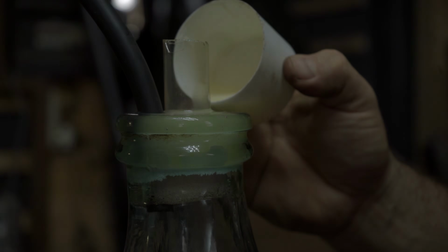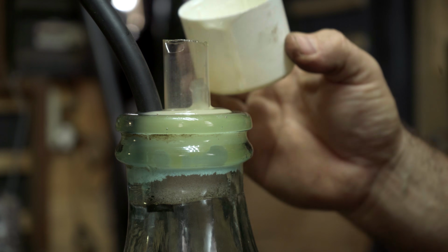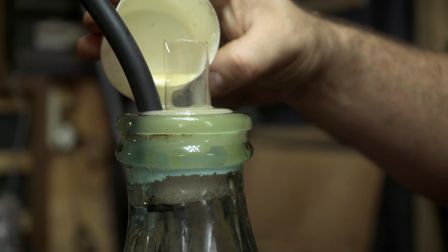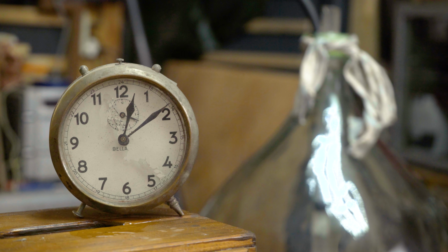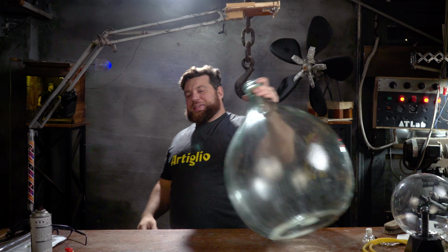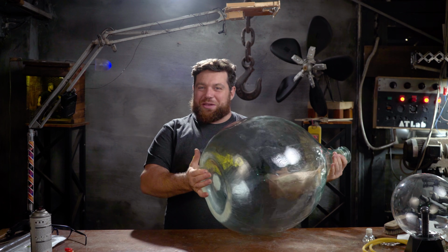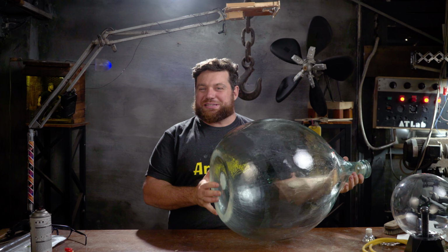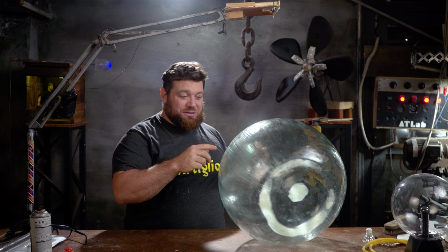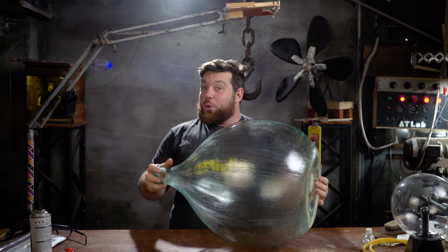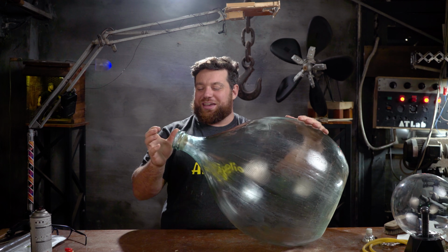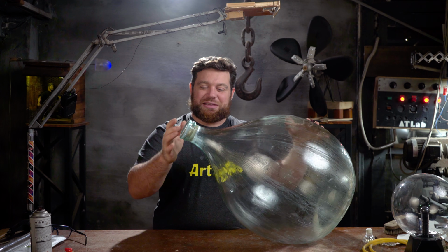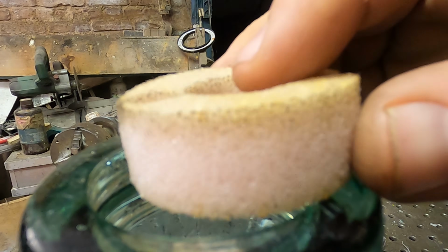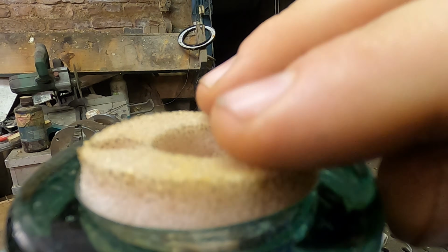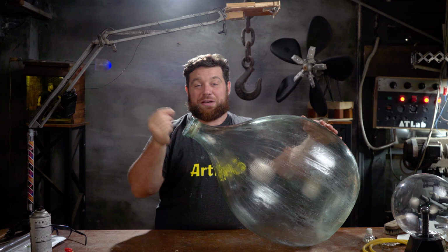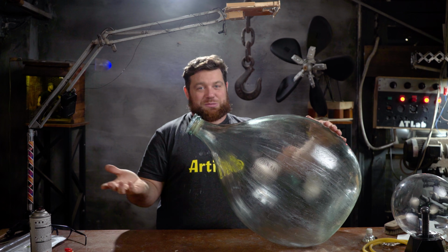But do you remember before, when we started to seal the glass container and let the epoxy cure for 24 hours, a huge mess happened in these hours. Everything was working perfectly, but I was distracted and I didn't see the epoxy resin was flowing into the foam that was closing the gap on the top. I don't know why, probably the foam is a little bit porous and the epoxy can flow inside. Maybe that's the reason why.